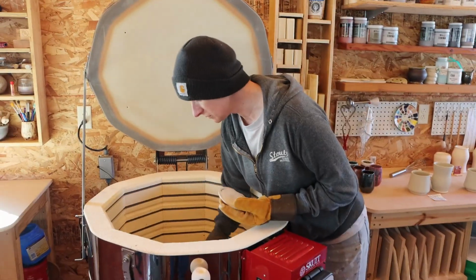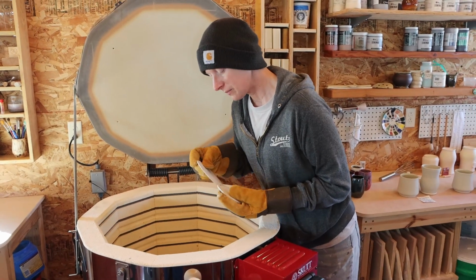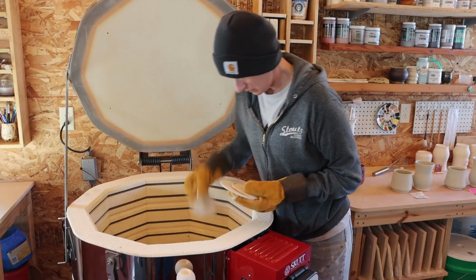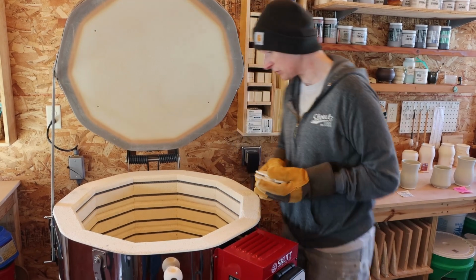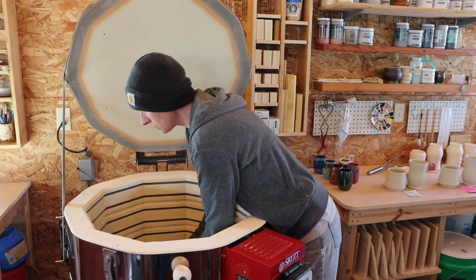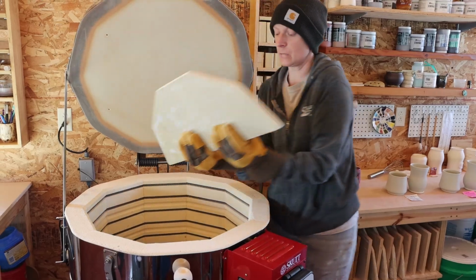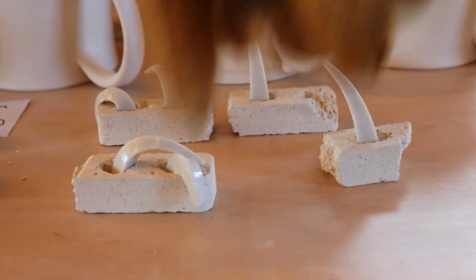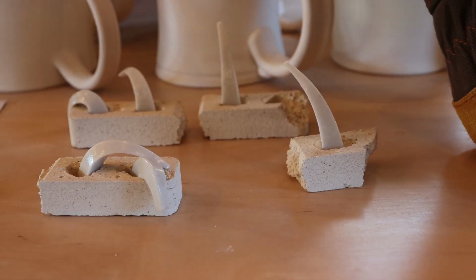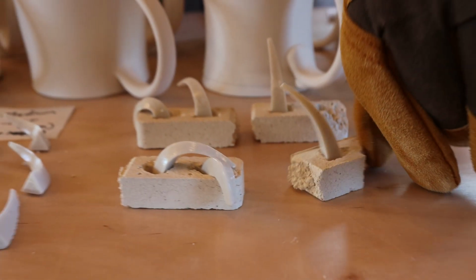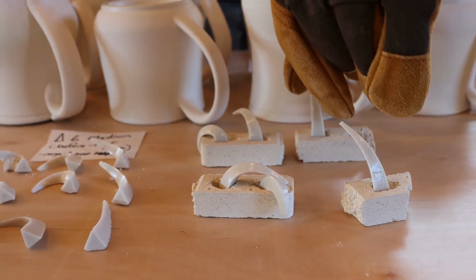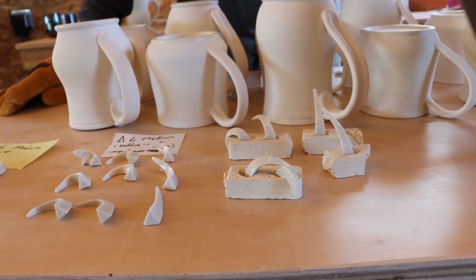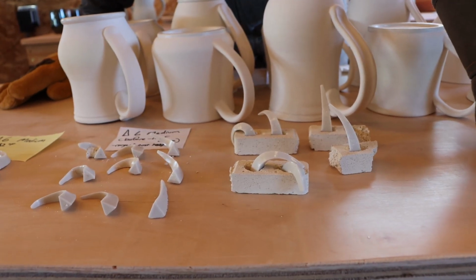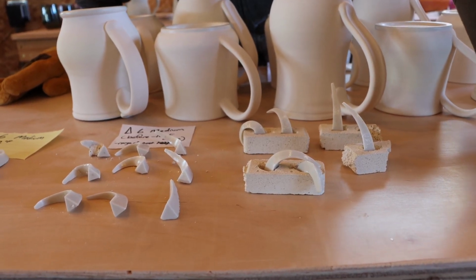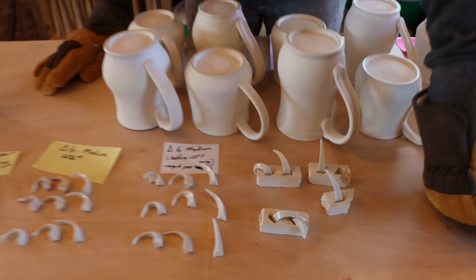But so far, our tricks to figure out the heating in the kiln are working. Well, we'll see based off this next cone that I can kind of see. And when we tested, the middle shelf was too hot. Correct. So the 6 is bent. It probably would have bent better, but it landed on top of the 5. How rude. So I think it probably would have curved over. And the 7 is just bent. It looks a little bit more than the top shelf, but not bad. So I think that's probably close to a true cone 6 also. Yes. Probably within the allotted range.